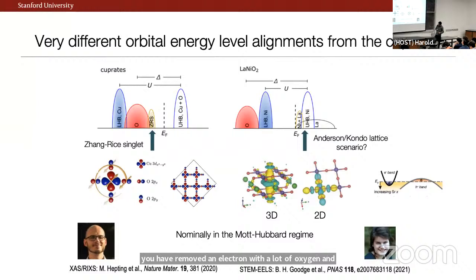So again, jargon aside, we have a large body of evidence that this is a way to think about hole doping the system. And so labels aside, we have the same ingredients, but we're now one over on the periodic table, a lower oxidation state, and a lot of these orbital levels have aligned in a very different regime. And so the upshot of this is that we have a piece in terms of the electronic structure that looks very much like the cuprate problem. But we have an additional piece that is a second electronic band or pathway.